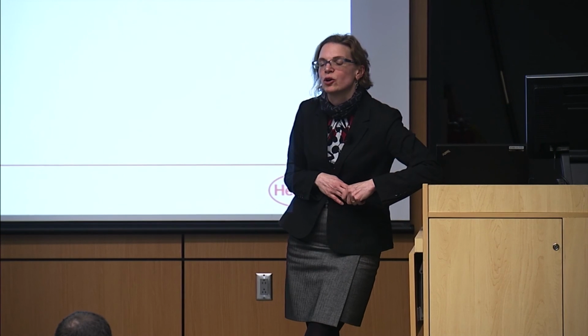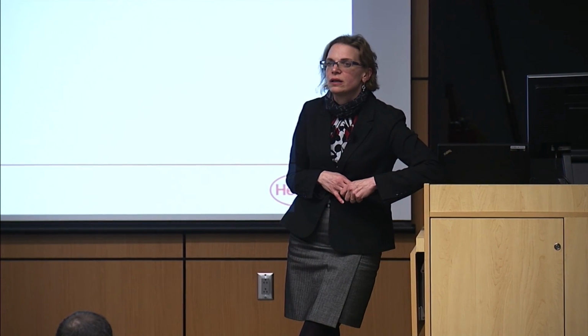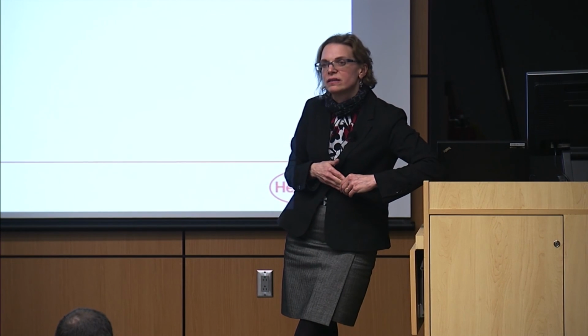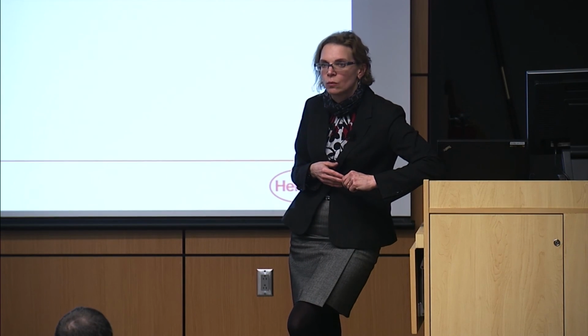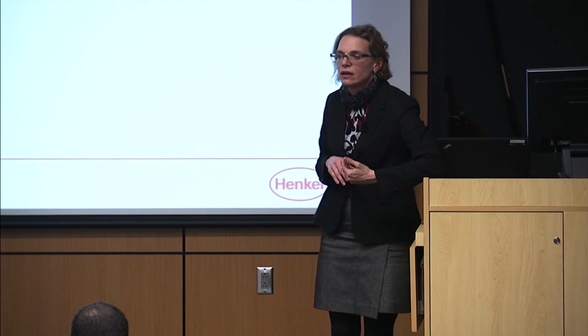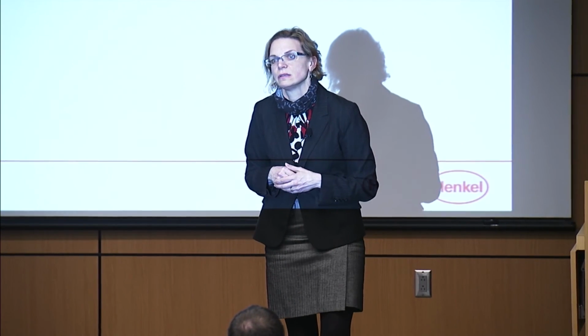Yeah, absolutely. In lower pressure contacts, we occasionally see that sort of behavior where there will be formation of a gas layer, but it's typically very rare because when you're looking at an industrial lubricated contact, it's typically relatively high pressure. If you were going to look for a gas layer to form, you would actually start with a gas. So you would work with something like an air bearing. We do try to avoid gas formation, and it's a very sensitive discussion because typically we're not worried about generating a gaseous barrier. We're worried about the release of materials into the environment. So any sort of outgassing would be very, very negative in a typical situation simply due to environmental release.